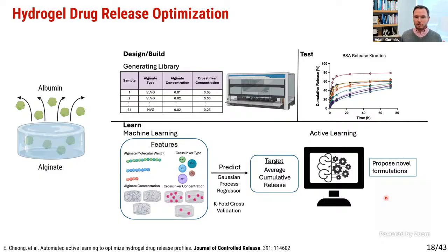And so we wanted to test the idea that self-driving lab operations, automation, and machine learning are going to be useful for optimizing the release profile of a hydrogel system. This is our classic design, build, test, learn, closed loop workflow, where we've got all these different possible combinations of additives for a hydrogel. We then use the automation to actually prepare these hydrogels and then track the release of our cargo.